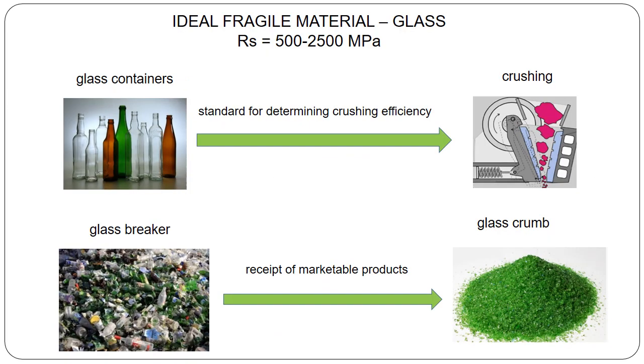The standard for determining the effectiveness of the use of crushing and grinding equipment is glass, which has high compressive strength and low impact resistance, which is destroyed by mechanical action without noticeable plastic deformation and belongs to ideally brittle materials along with diamond and quartz of all types of glass. Glass containers with standardized mechanical properties and geometric dimensions are accepted as the starting material. At the same time, interest in obtaining glass powder is currently growing in the world. This problem is relevant, as it is associated with a wide range of properties that make simple and special glass powders a universal material.